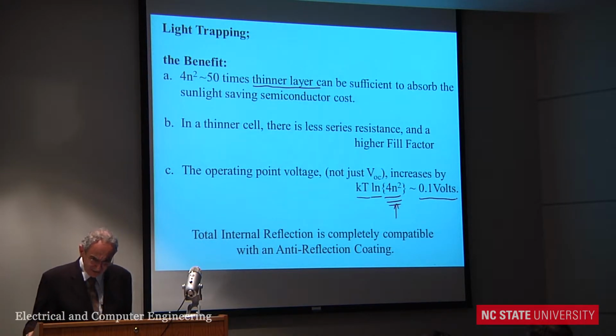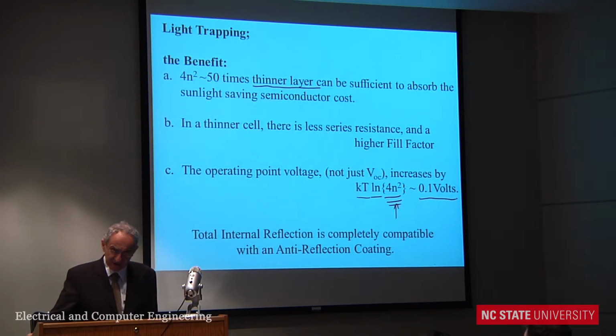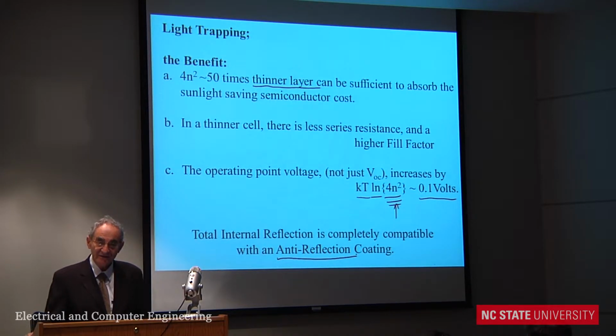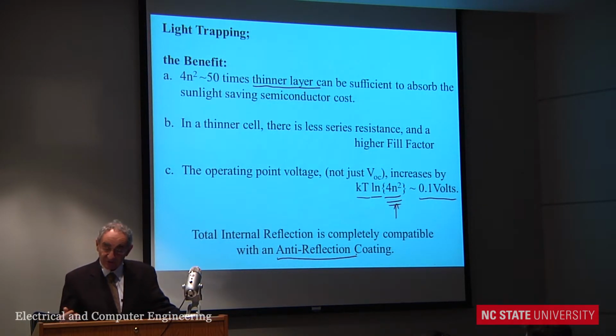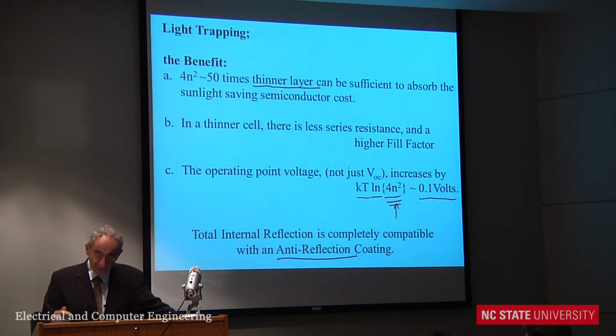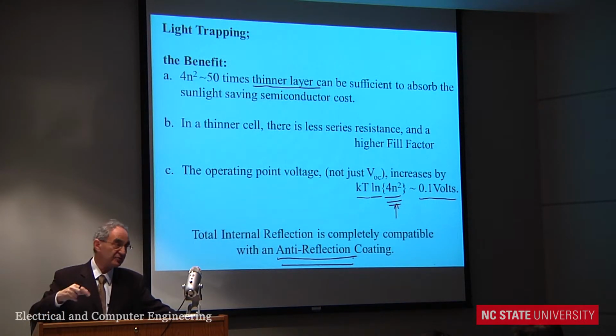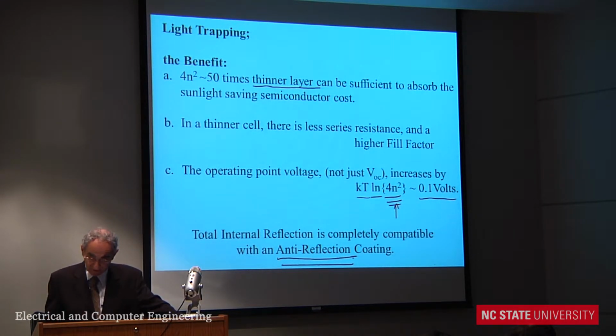But here is a problem in the English language. They say, great, you're going to take advantage of total internal reflection to trap the light. How is that going to be compatible with the anti-reflection coating that all solar cells need? So you get worried. Total internal reflection, anti-reflection, they're contradictory. But actually, they're not contradictory. Every solar cell should have both. If you're in the escape cone, you have to be concerned with the anti-reflection coating. But the anti-reflection coating has no effect whatsoever on the total internal reflection, which is influenced only by the refractive index ratio between the inside and the outside world. So it's just a problem of the English language there.